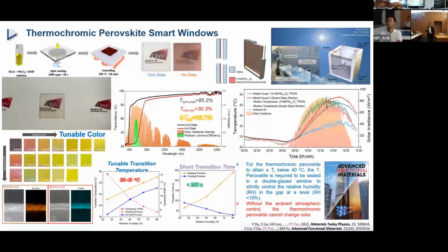We can also adjust the material composition to control the color, and the transition temperature can be controlled within about 25 to 45 degrees Celsius. The whole transition process can be finished in a couple of minutes. However, for this kind of perovskite material, there is a fatal issue: in order to trigger the thermochromics, the humidity needs to be controlled within a very precise range, around 20% or even lower. So for commercial use, the only way is to put this perovskite material in a double-glazed window so that we can control the humidity inside. But as a result, the installation and maintenance cost will be very high.